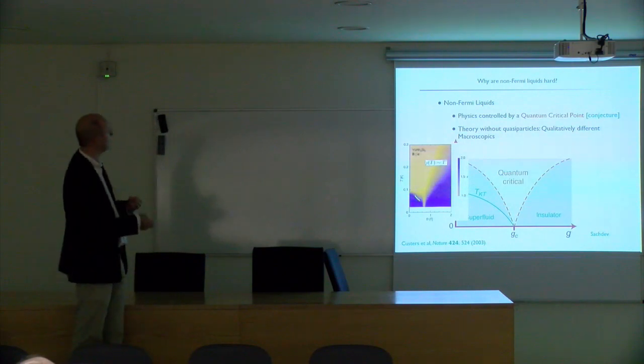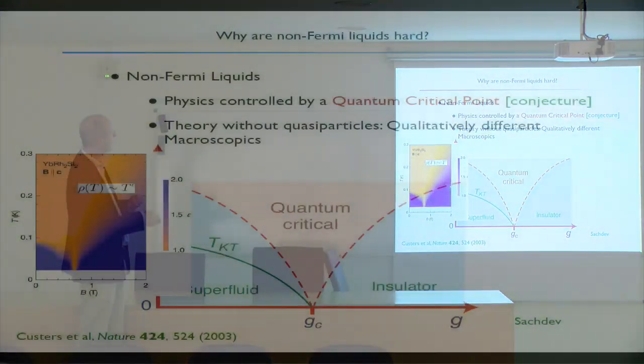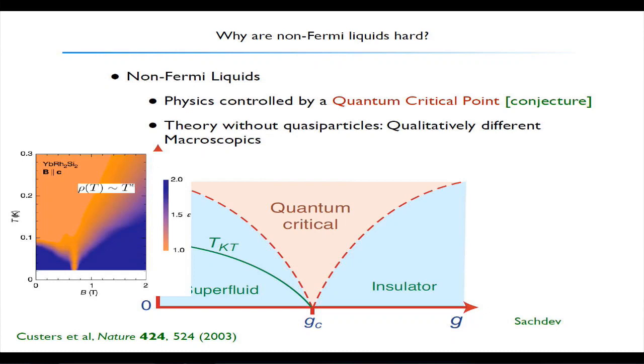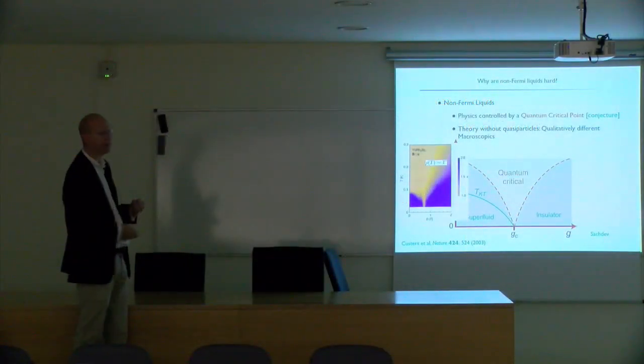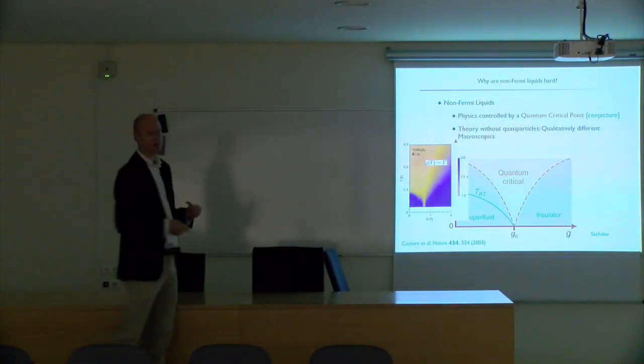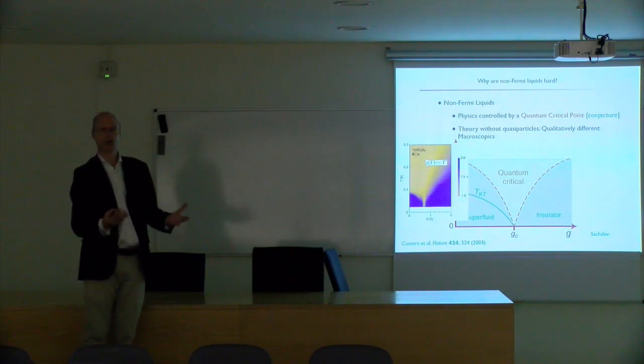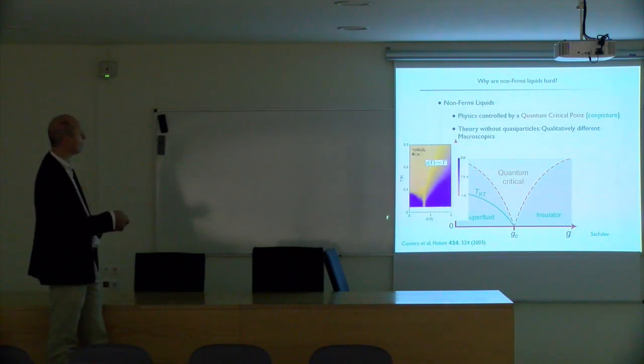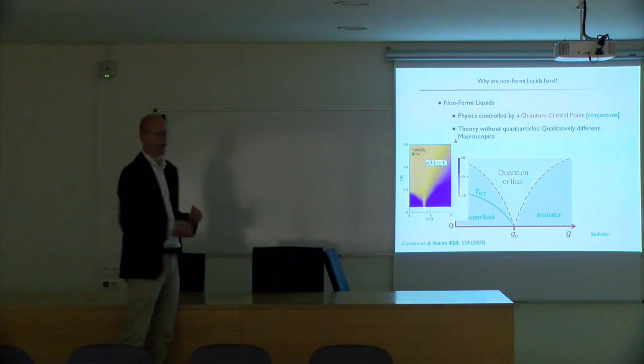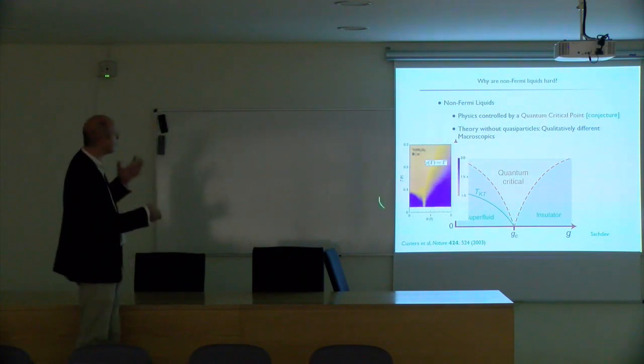And this is an example of a so-called heavy fermion system where you see this type of behavior. What is plotted here is the resistivity as a power of the temperature, where in these regimes, this is an ordinary metallic system. You see indeed the T squared behavior. The exponent of T, which is plotted here in blue, is 2. But here you see this fan-like behavior where all of a sudden the exponent changes to 1, just like in the strange metallic systems. Here the extra parameter that changes the phase transition is the magnetic field.